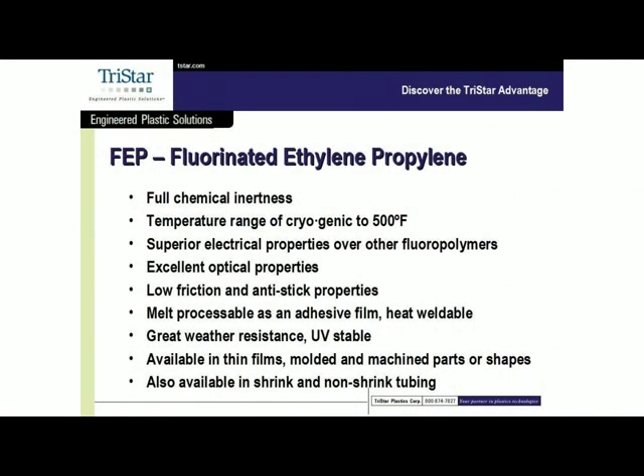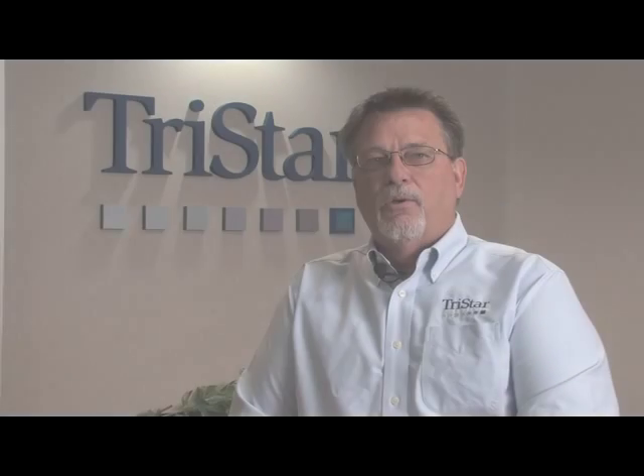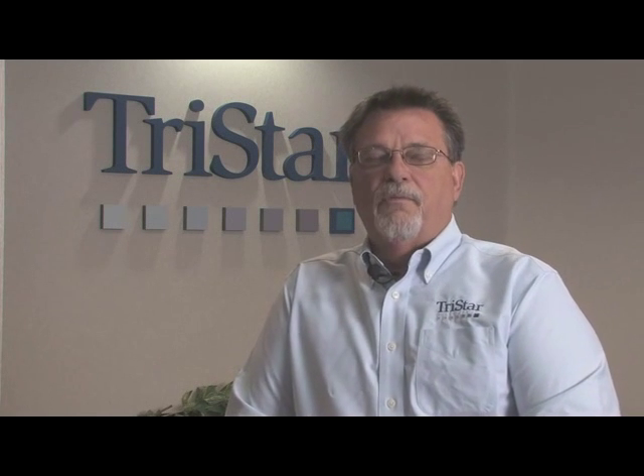FEP is pretty commonly used as a film adhesive. Because of its melt temperature, we can use FEP to bond other fluoropolymers to a substrate. So if you have, say, a Rulon material and you want to bond it to steel, but you don't want to use a cold bond or an epoxy, there is a special grade of FEP that can, in fact, be used as a melt processable film adhesive. Very, very strong. Not as strong as most epoxies, but certainly strong enough for most applications.